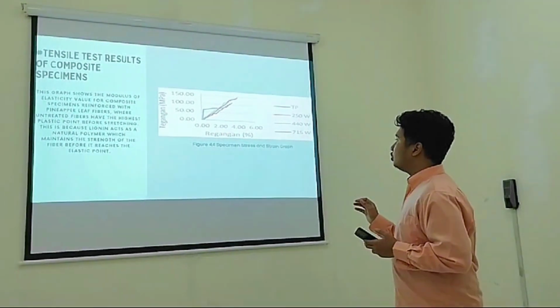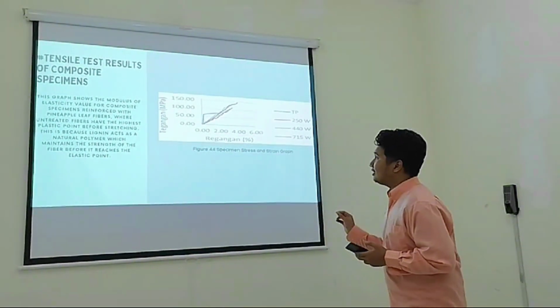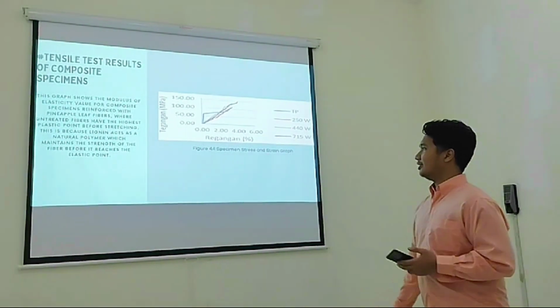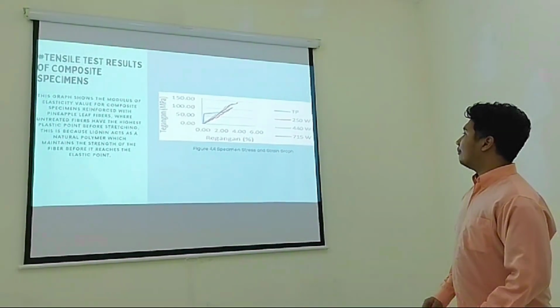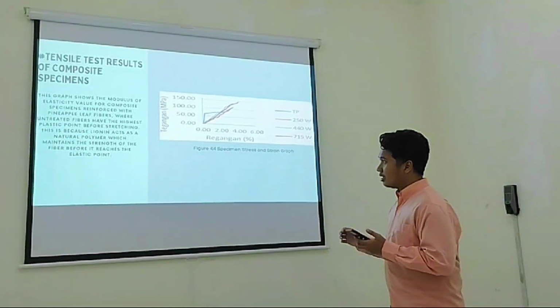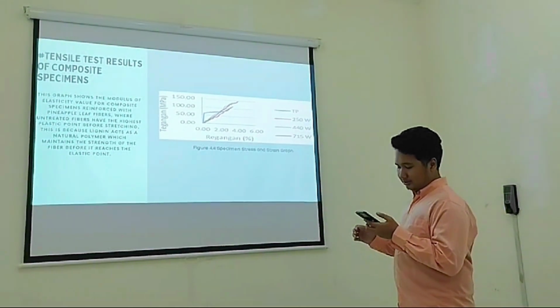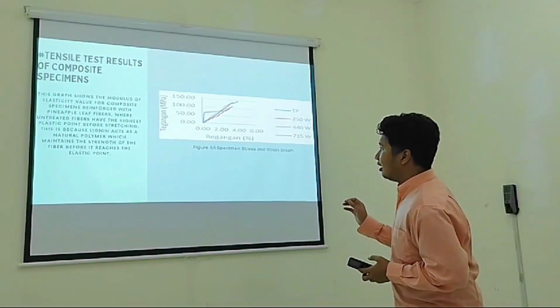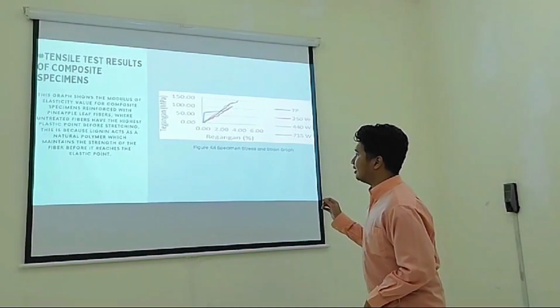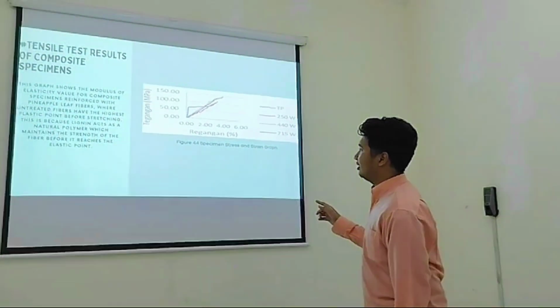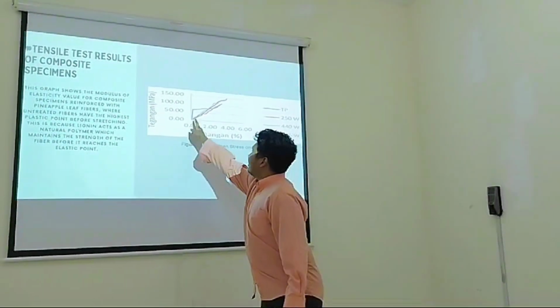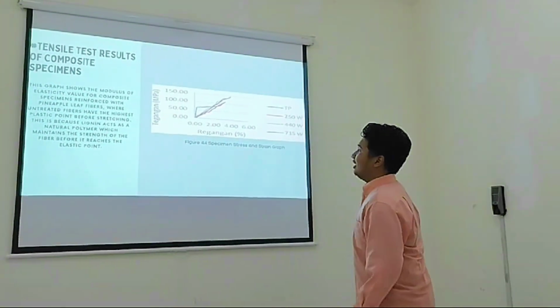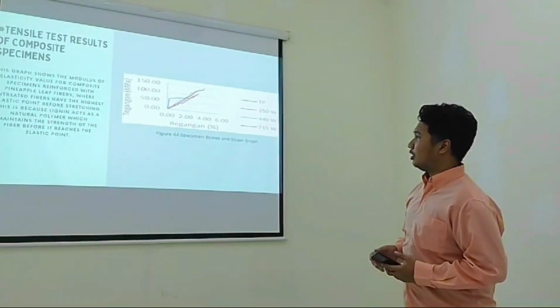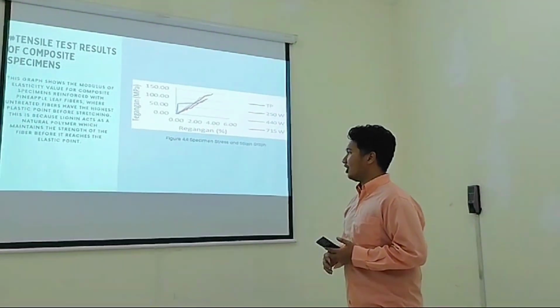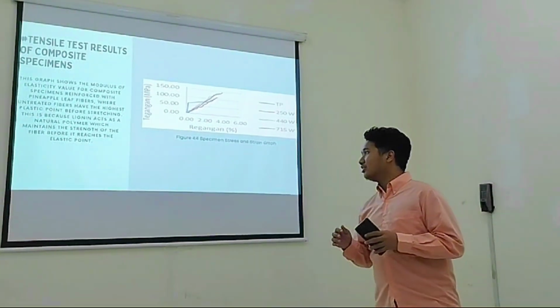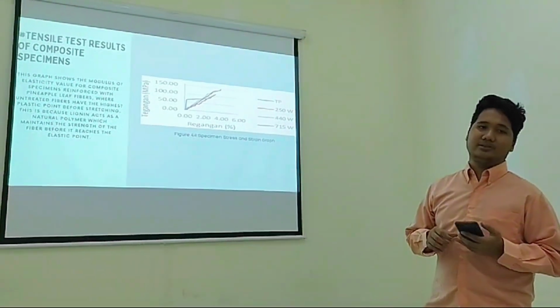This graph shows the modulus of elasticity value for composite specimens reinforced with pineapple leaf fiber, where untreated fibers have the highest plastic point before stretching. This is because lignin acts as a natural polymer which maintains the strength of the fiber before it reaches the elastic point.